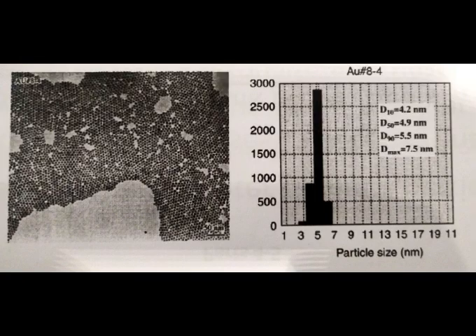And this increase in surface area leads to a much higher surface energy. So the nanoparticles are much more reactive, and they want to clump together. This is really what those organic coatings are there to prevent. They're like little guardians, keeping those nanoparticles from glomming onto each other and becoming unusable. And the presentation even mentions gas evaporation is one of the methods used to prepare these. So there's a lot of control that has to go into making these things, it sounds like.